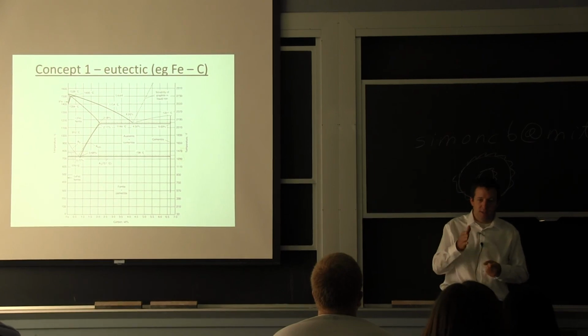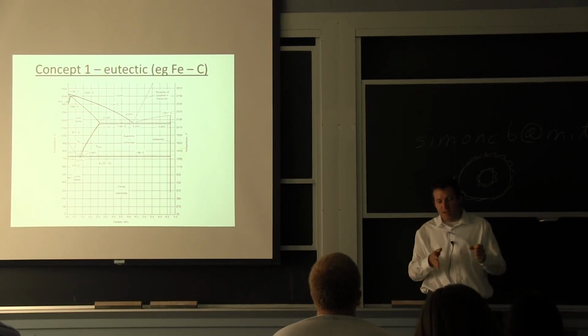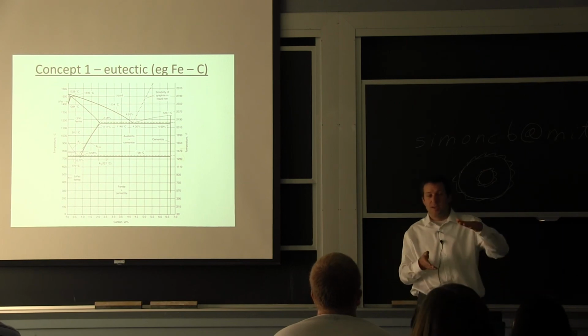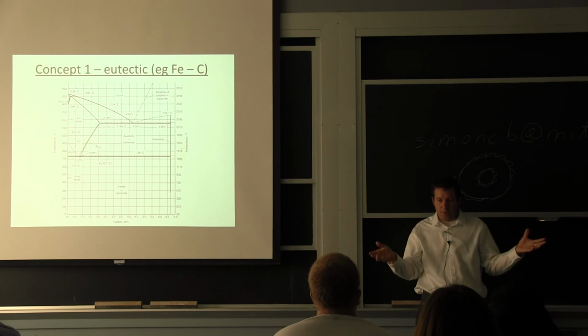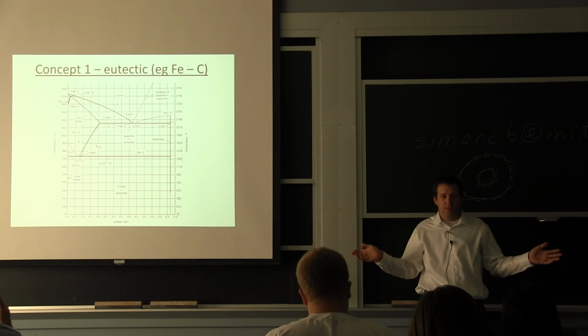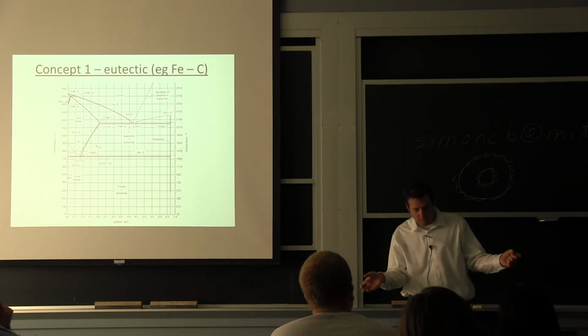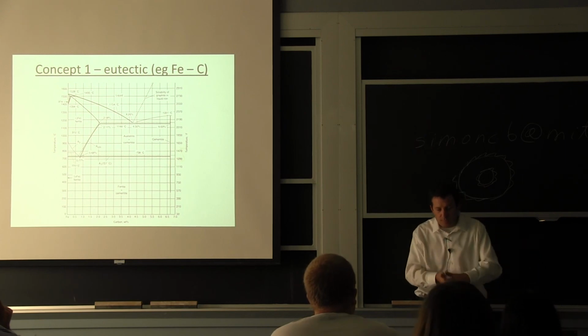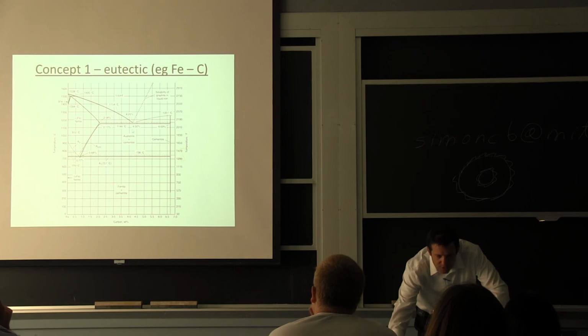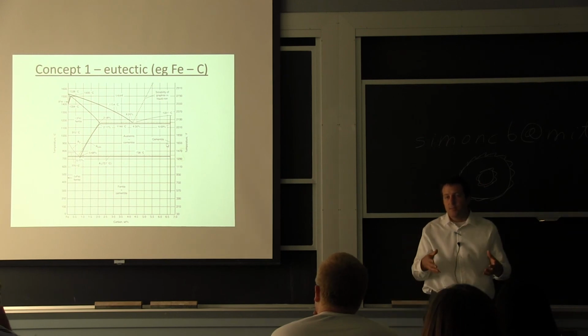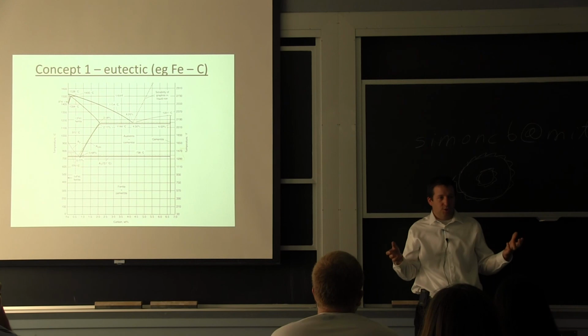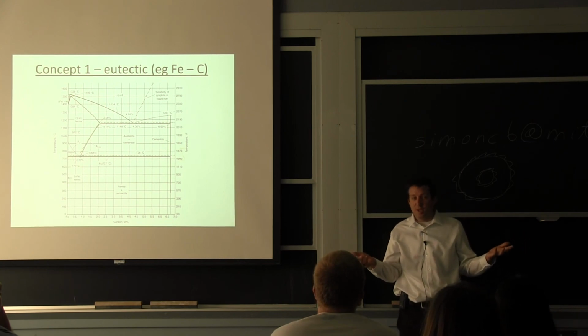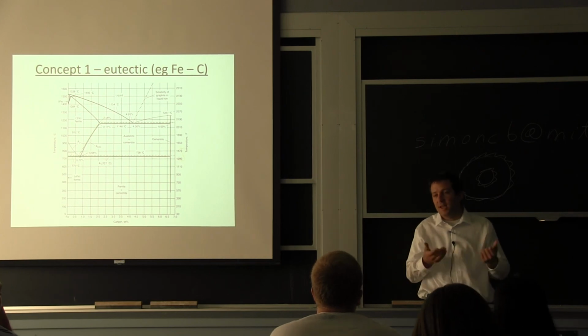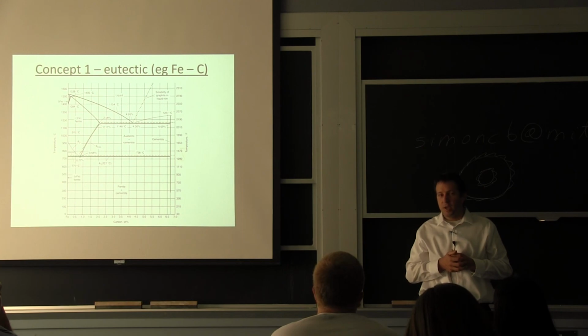It's great because if you have the exact eutectic composition, you wouldn't have all that segregation issues and these things that I was talking to you about, because you essentially, in terms of the thermodynamic, the whole alloy is perfectly happy in the liquid state with that iron and 4 or 5% carbon. And then from one temperature, as soon as you go across it, everything wants to become solid. Yeah, but it will separate. It will separate in this phase here, so an iron-rich phase and a carbon-rich phase, but all at the same time. So it's a way to minimize the segregation also, but it makes for a relatively brittle material because you put a lot of carbon into it. You have a phase that's very brittle, and that's why cast iron has a lot of limitations. There are ways to